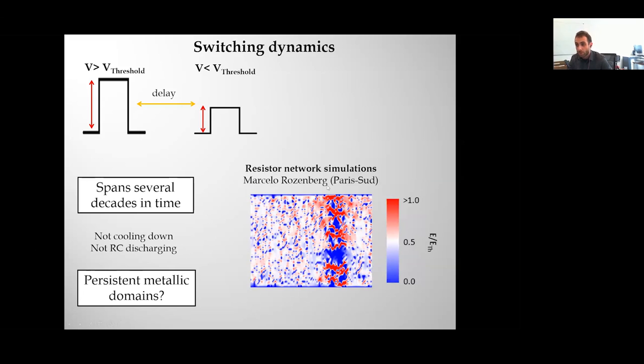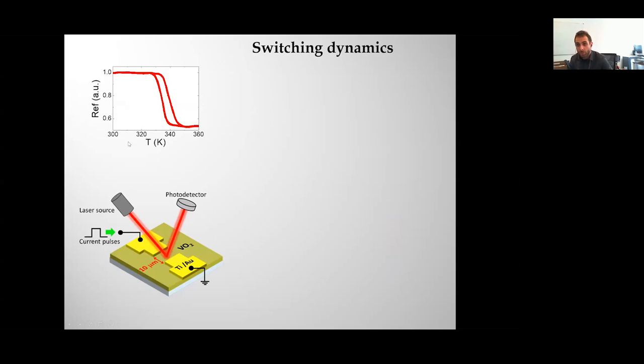Marcelo Rozenberg in Paris, with his group, did some resistor network simulations. This is a 2D map of the electric field in the area between the two electrodes. Blue means low electric field, red means high electric field. What they found is that even if you have a small amount of residual domains, the effect of those residual domains on the electric field is very large, because they can focus the electric field locally. Even though your average electric field is not close to the threshold field, locally it can get close to the threshold field because it's inhomogeneous. This was only a hypothesis, so we needed to measure if it is true, if we have some persistent domains that are very long-lived. We needed a probe, a proxy that allows us to determine the amount of metallic domains that we have.